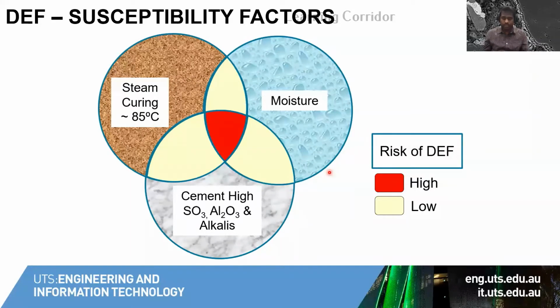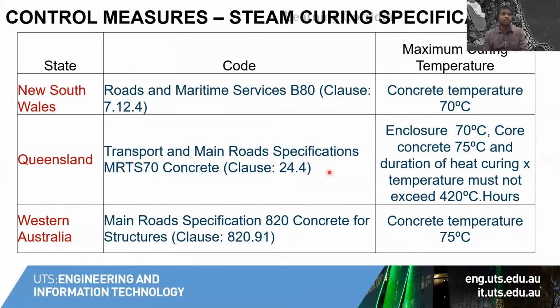So we basically don't have control over the environment. All the control measures to control DEF basically try to control the steam curing and the cement chemistry. You can see standards actually restrict curing temperature. Here in Australia, different states can have different curing specifications, but more or less all the specifications restrict the curing temperature to 70 degrees Celsius. In some cases, for example Queensland, it also controls the core concrete temperature not to go beyond 75 degrees Celsius. So this is one way of trying to control a DEF related issue.